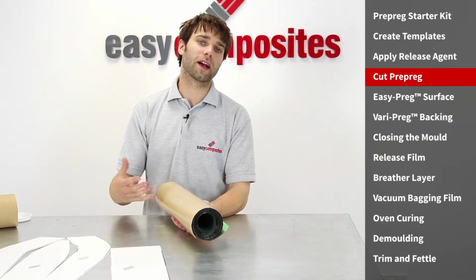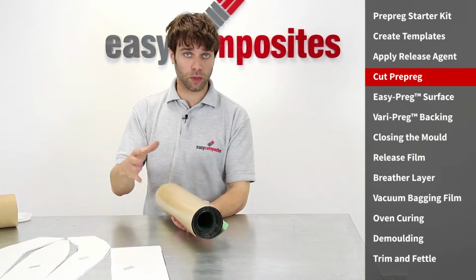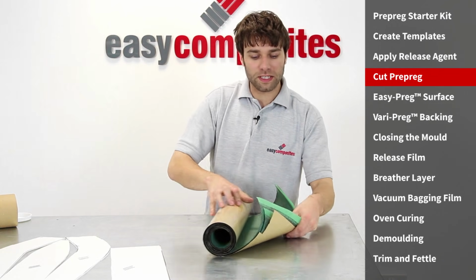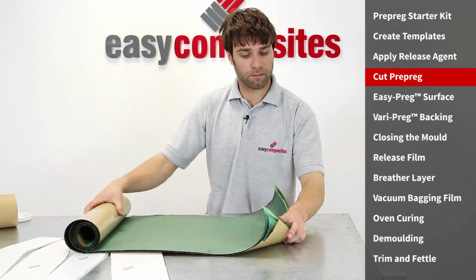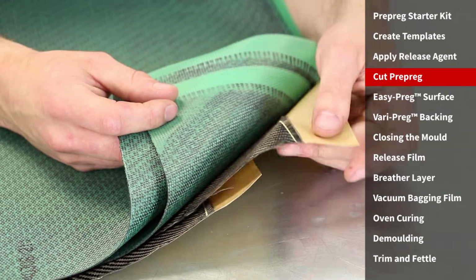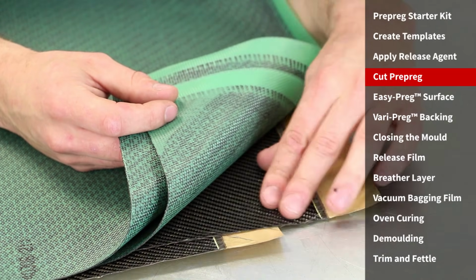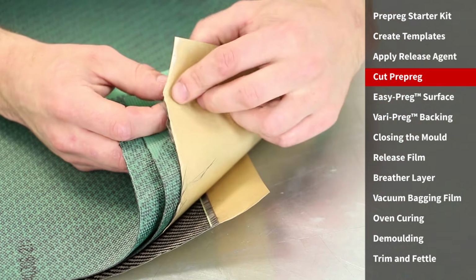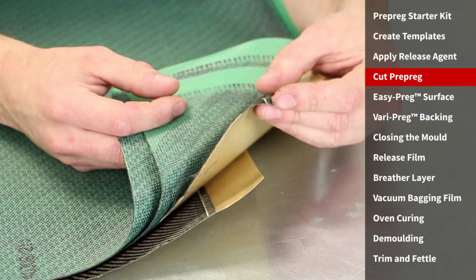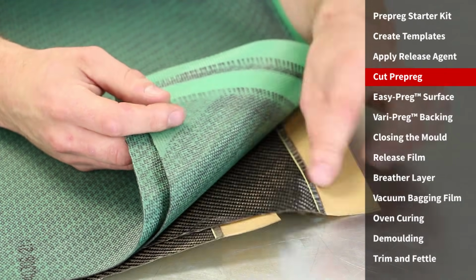If you've been storing your prepreg in a freezer, make sure it's fully defrosted before you unpackage it. We need a piece of the surfacing and a piece of the backing ply of the prepreg. The special prepreg surfacing ply you can identify by the fact it's dry on one side. This prepreg really is the secret behind getting a pinhole-free surface finish.